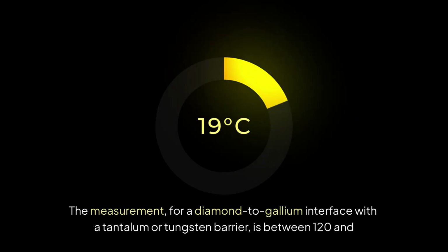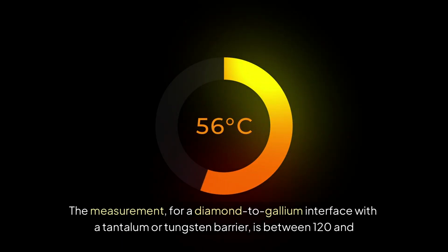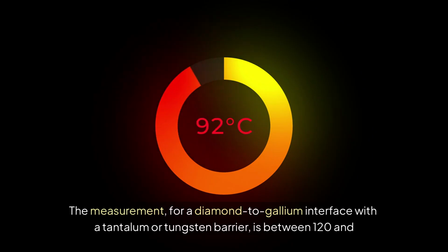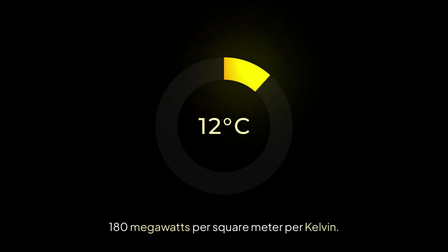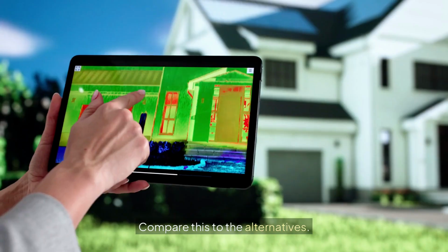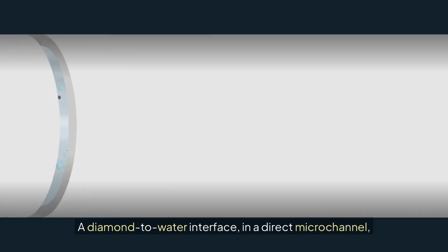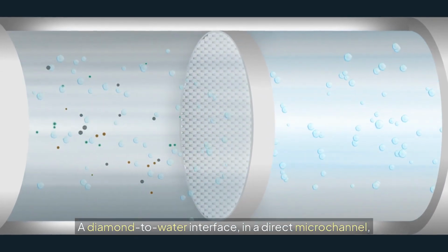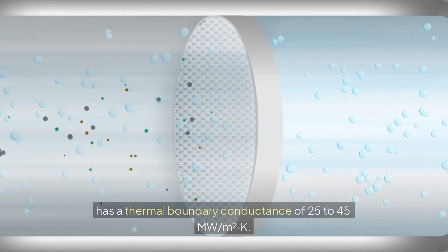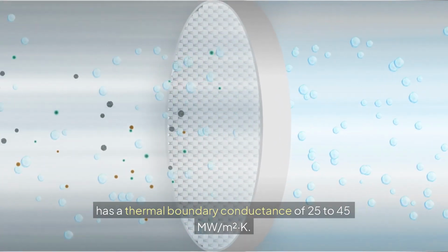The measurement for a diamond to gallium interface with a tantalum or tungsten barrier is between 120 and 180 megawatts per square meter per Kelvin. Compare this to the alternatives. A diamond to water interface in a direct microchannel has a thermal boundary conductance of 25 to 45 MW/m²K.